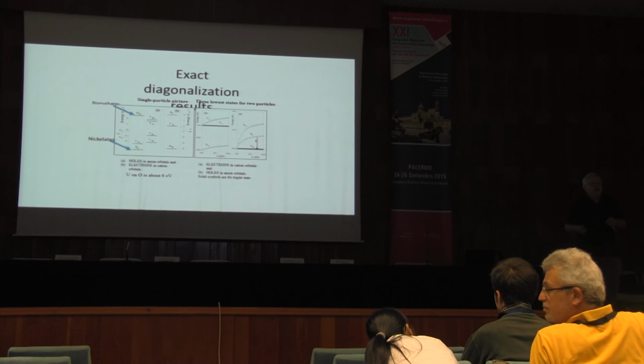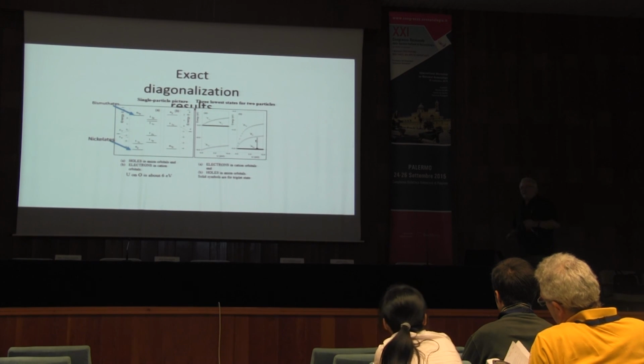That is why I say that these two holes in an EG state of oxygen molecular orbitals actually have a very strong triplet stabilization. That is not because of exchange. That's because of the fact that they are fermions and that the U doesn't want two electrons or holes to be on the same site. There are some very simple little calculations you can do to prove to yourself that you can have very strong energy differences with spin states in a finite system like that, just because of kinetic energy terms.